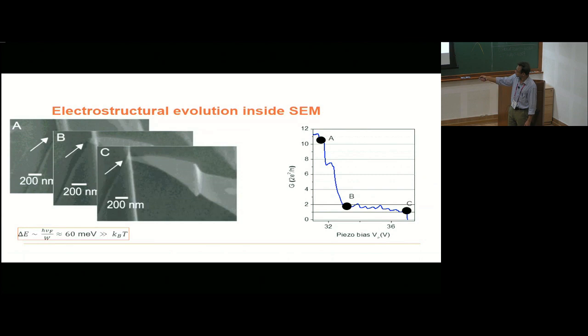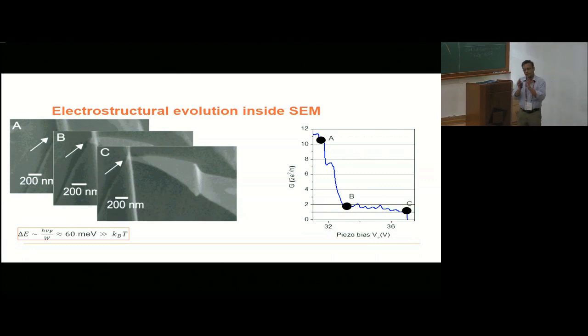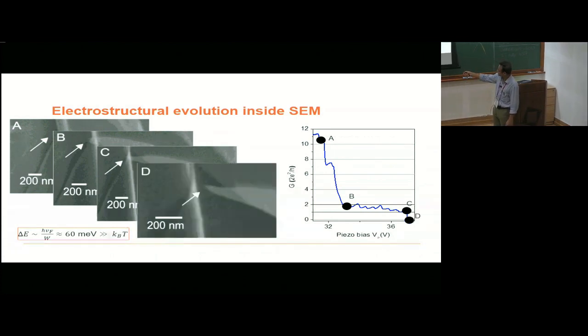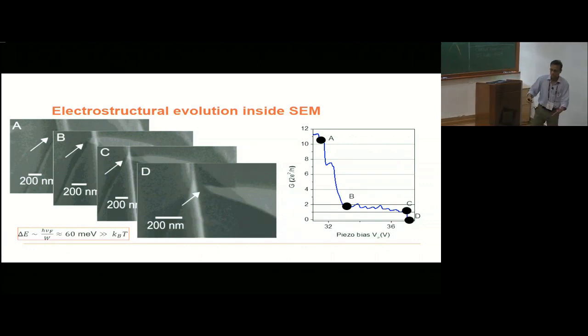Farther you go, this is where the contact area is extremely small. It's less than 5 nanometer, which is, according to quantum confinement, the electrical transport through this region will be extremely small. Should have been insulating, but instead what we are seeing, the conductance is essentially saturating towards exactly 2e squared by h. And then when you pull it up completely, you can see this contact has been detached, and you essentially have a drop in conductance, and the system goes into the insulating phase.